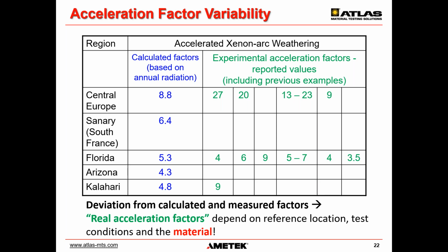As I told you before, if you only do quick calculations based on radiant exposure, you neglect the material in total, and the material is the key factor you are interested in when you are doing a degradation study. True acceleration factors must, and I repeat that, must be experimentally determined by using the outdoor and accelerated test data for the specific materials and the specific laboratory test and the specific outdoor location with a specific sample tilt and orientation, etc., etc. This means you need the real-time outdoor exposures and climates of interest to determine acceleration factors.